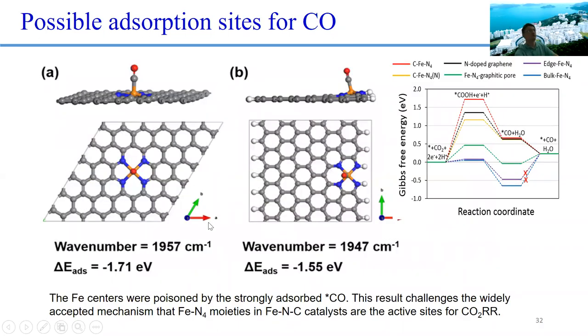So we did the DFT calculations. First, we put the CO on this perfect iron nitrogen carbon site, on top of the iron. We can predict the wave number of the CO and also the total energy very well. We can see that the first step is very easy because the adsorption of the CO2 on iron is very straightforward. But the last step, removing the CO, is very difficult because the adsorption of the CO on iron is too strong. So in this case, we don't think this pathway is feasible.